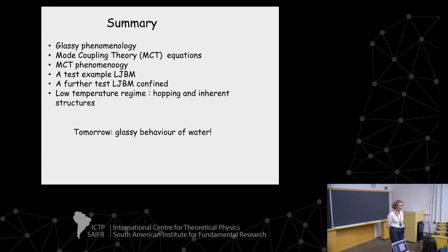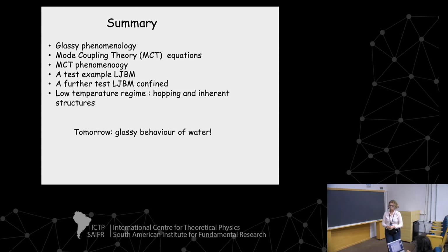And also they had to change the mixing rules of interaction, which usually we do with the averages, and these are called Lorentz-Berthelot mixing rules, and instead they had to change the parameters of mixing so that they could mix more. Otherwise they tended to make crystal also this one and separate. So they twisted a bit the parameters, and made this Lennard-Jones, Kob-Andersen binary mixture.